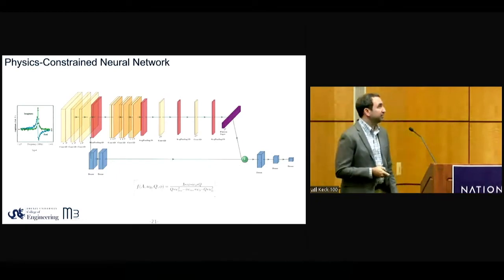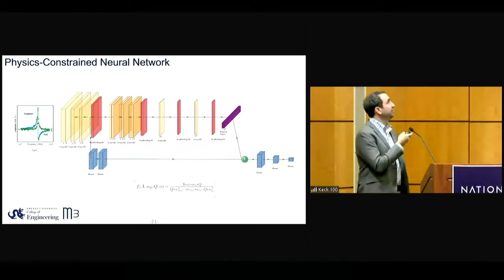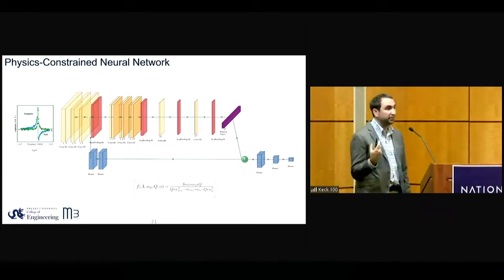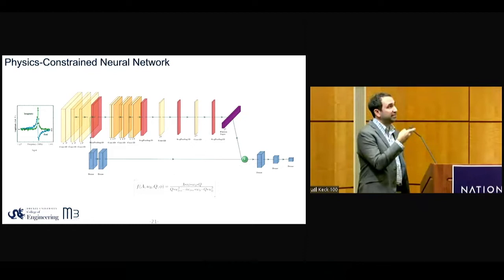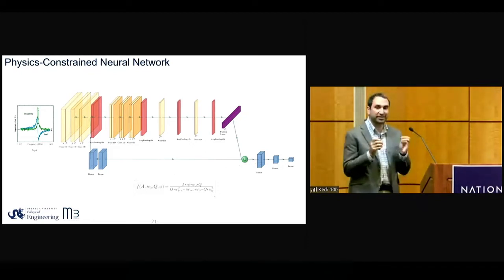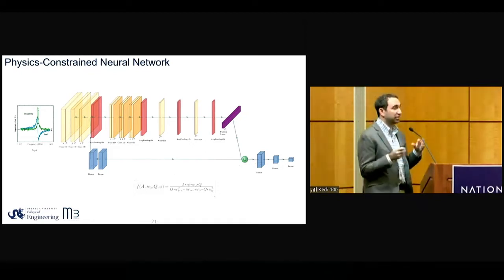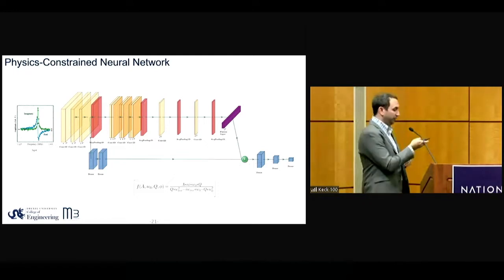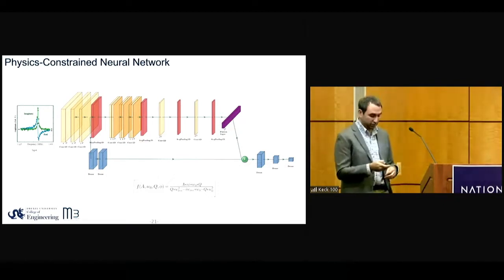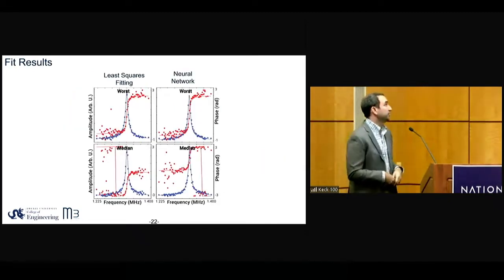So what we did is not that complicated. We take the raw data and use conventional 1D convolutional neural networks. We do some little tweaks with message passing that help. There's a lot of little tricks that make it perform better, but the general concept works pretty easily. At the end, we have a dense layer that predicts the 4 parameters needed for the empirical function. And because this is still differentiable, we can use auto differentiation, train this end to end, and train this completely unsupervised, but still obeying the physics.